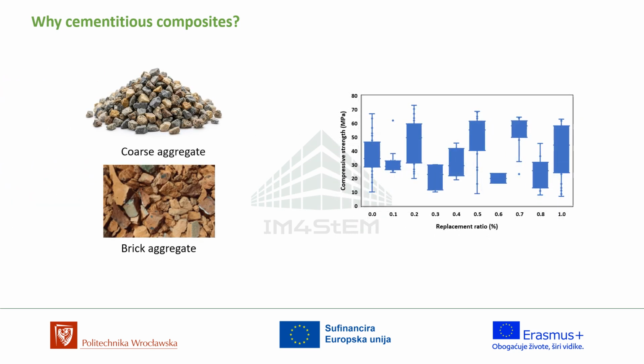Similarly, the results are equally encouraging when replacing coarse natural aggregates with crushed brick particles. Although porous ceramic aggregate has a lower individual particle strength than, for example, natural basalt or granite aggregates, properly designed concrete mixtures still achieve high performance. It can be seen that even with 100% replacement of natural aggregate, waste aggregate still achieves promising results. It's due to, of course, the other components of cementitious composites.